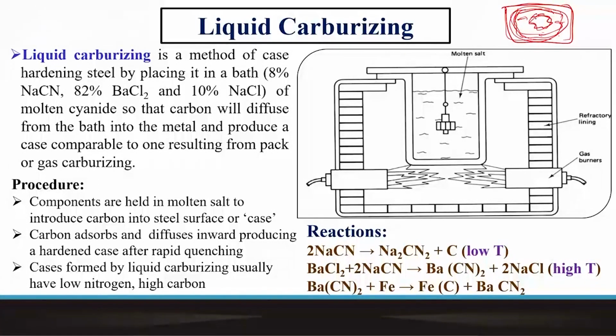So unlike that situation, here we are dealing with liquid carburizing or liquid bath carburizing. So in this process, we are obviously not only using a different state of matter, liquid state, but also the charge is different. And basically we are dealing with cyanide material, and the very name certainly would convey a very unmistakable message that we are dealing with an extremely dangerous material, and also which decomposes into sodium cyanamide group of materials, and eventually through certain reaction it produces the barium cyanide material. And the most important thing is that this barium cyanide undergoes decomposition when it comes in contact with ferrous substrates and releases carbon, and that too carbon in the nascent, atomic form.